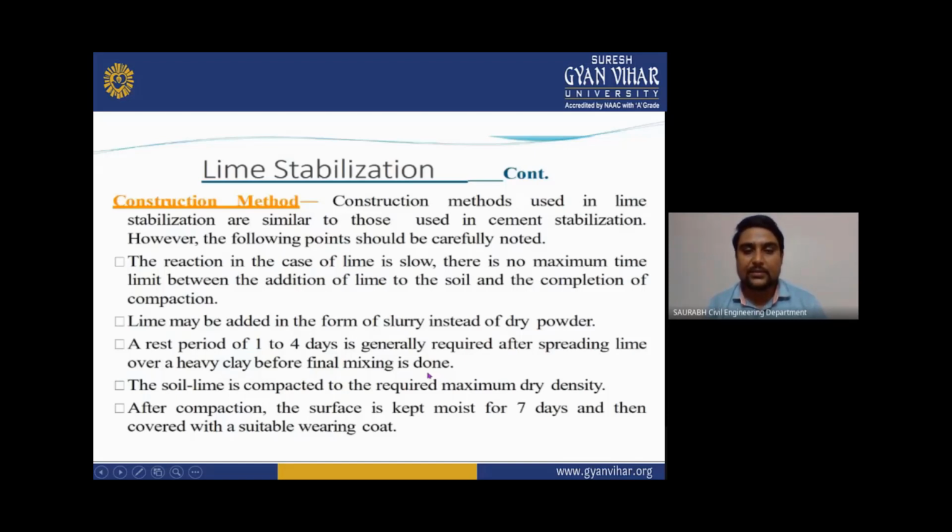Lime may be added in the form of slurry instead of dry powder. A rest period of 1 to 4 days is generally required after spreading lime over heavy clay before the final mixing is done. The soil-lime is compacted to the required maximum dry density. After compaction, the surface is kept moist for 7 days and then covered with a suitable wearing coat.